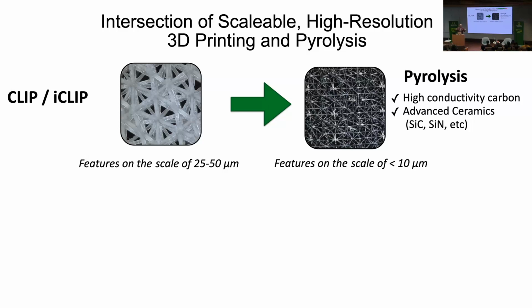And it has to have a high surface to volume ratio to outgas, and it shrinks isotropically into a fiber. Nobody pyrolyzes three-dimensional objects because you can't outgas and they fracture. Well, when you stitch together lattices, this looks like fibers to me. And we are now pyrolyzing these three-dimensional structures and designing 3D printable resins that optimize the formation of carbon, silicon carbide, silicon nitride, new boron-based materials, and they shrink isotropically when they're designed properly and printed properly.